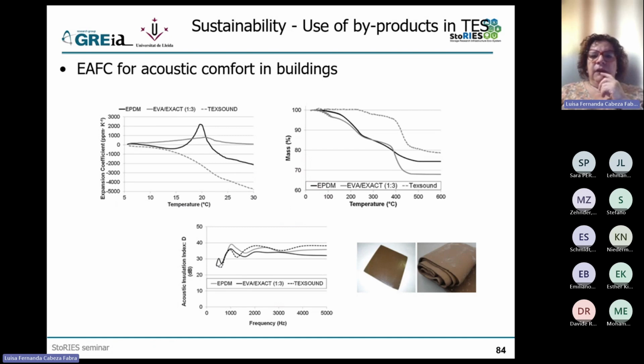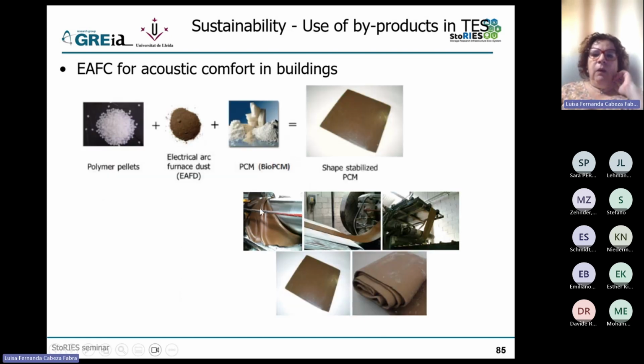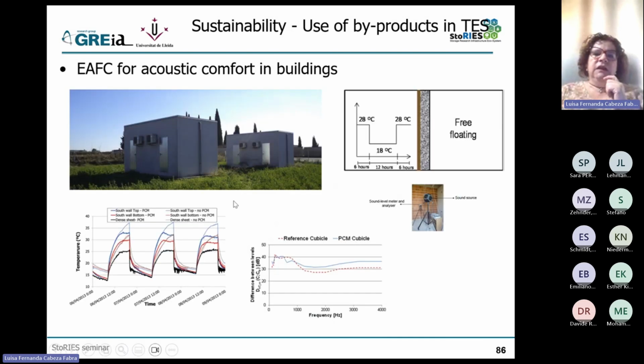And then, as I said, we characterized it completely, not only from the thermal point of view, but also expansion coefficient, the mass, the acoustic insulation, always comparing it to a commercial material, which is this Texsound. And we even went to an industry and produced several square meters, so not only in the lab, but in a real industry. So we saw that we could scale up from the point of view of production. And then we tested it in our cubicles in this setup that we have.